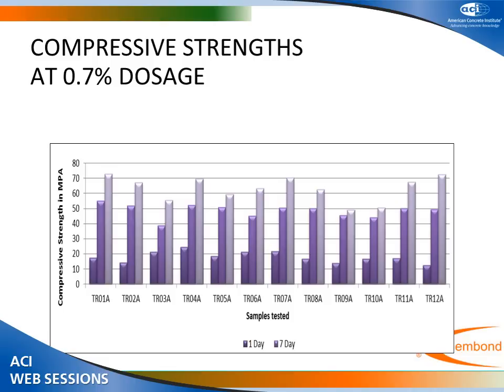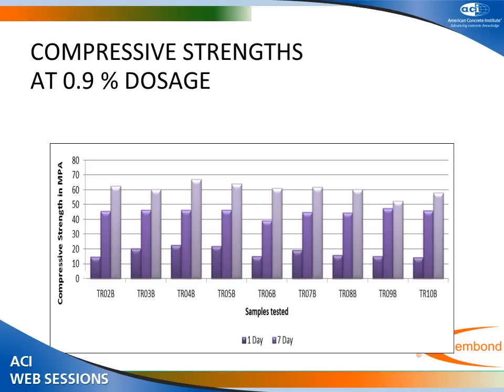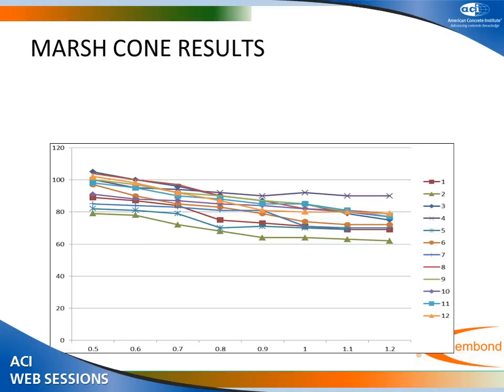Compressive strength, again this is the combination. So I think we have seen before, the compressive strengths are quite good for most of the combinations, and at 0.9% slightly reduced, but still more than 60. Actually, we did some Marsh cone tests for determining the dosages required. So we came to the conclusion that at 0.7% generally the PCEs and the 75-25 combinations were working well, whereas for the remaining combinations we required 0.9% to achieve the same viscosity as well as the time.